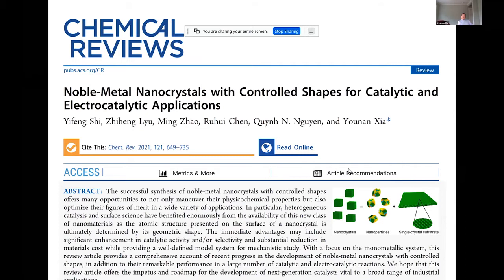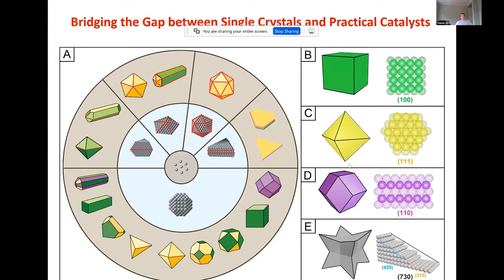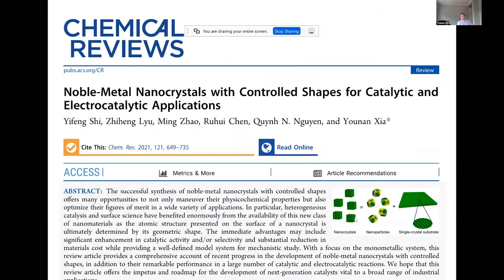And here I just want to quickly show you what's included in the review article we published. So basically, we make an argument that by controlling the shape of these nanocrystals, you will be able to control the specific arrangement of atoms on the surface. That could be the 1-0-0 facet for the cubic shape, 1-1-1 for the octahedra, and 1-1-0 for the rhombic dodecahedra, and so on and so forth. And by making these nanocrystals on a very small size scale, at the same time with well-defined surface structures, basically you can have something that can bridge the gap between single crystal substrates and the traditional practical catalysts.